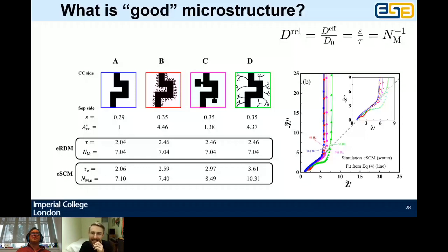Okay. How many SEM images do you need to create a useful training set? Good question. There's no straightforward answer, because also there are complicated questions around resolution, as always. So depending on the size of your features relative to the size of your domain, relative to the scale of your anisotropies and heterogeneities. We've been doing this for flow battery data, fuel cell data, all kinds of interesting data sets. And we found that different amounts of data are required for different systems. But a usual tomography data set, sort of 500 by 500 by 500 voxels will be the nice bit in the middle. That's loads of data already, as far as we're concerned.